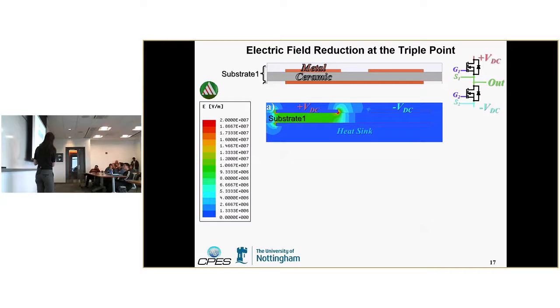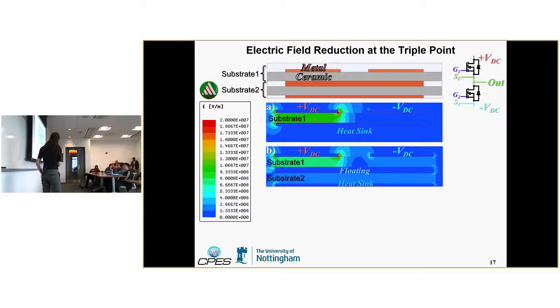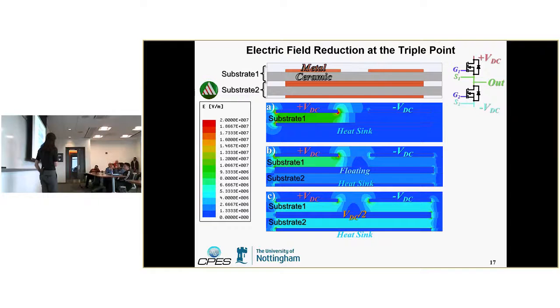So if you have the single substrate, this is an electric field simulation. You can see the high electric field at those triple points. Then if you add your second substrate and leave that middle layer floating, so this is still a simplified case, I'm just showing 2 patterns with your positive and negative DC bus on top. You can see your electric field is still heavily concentrated in this area. And then if you connect your middle metal to half of the applied voltage, or half the DC bus voltage, now you're getting a much more uniform electric field distribution, and the electric field at that critical triple point region is now distributed at all these corners, which is significant.